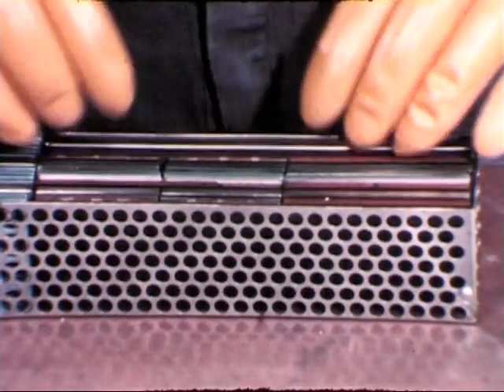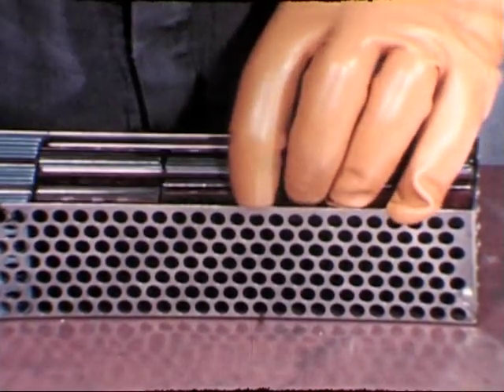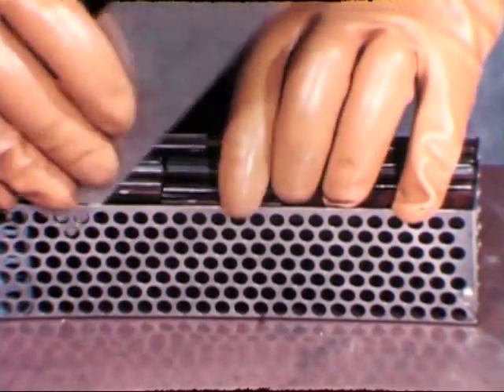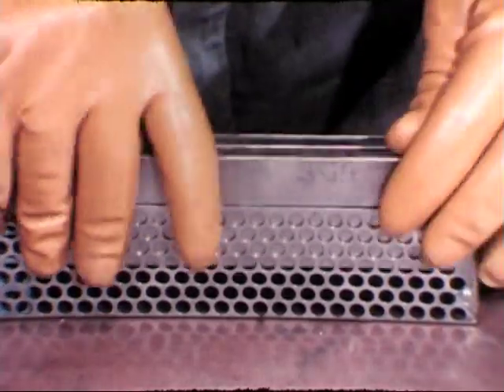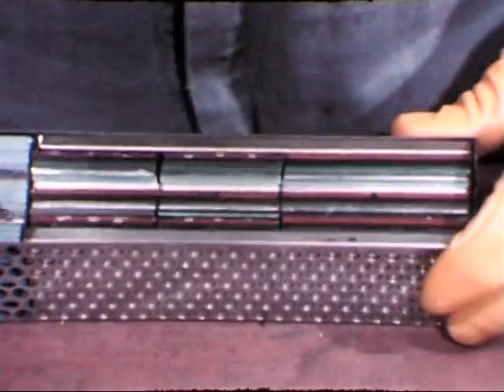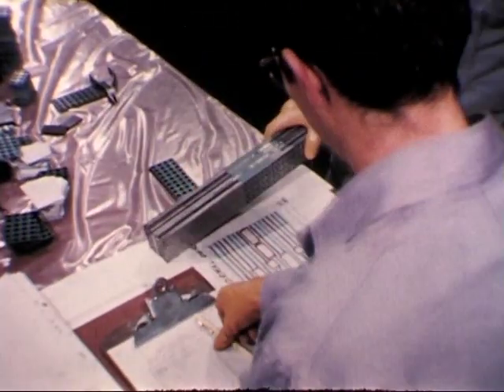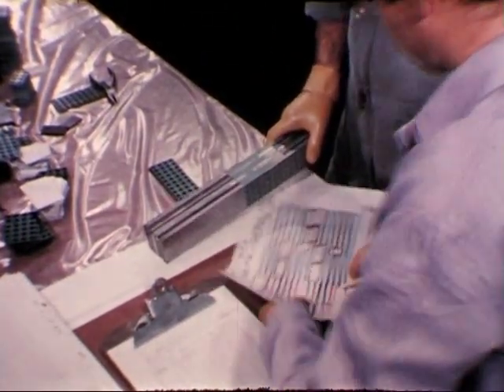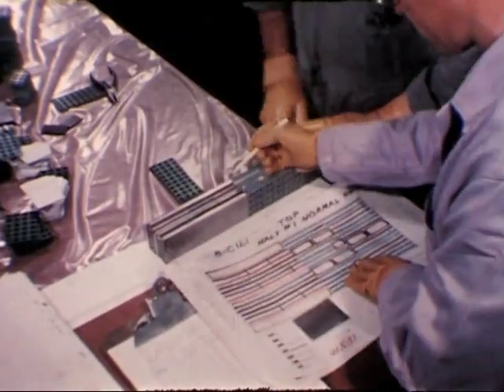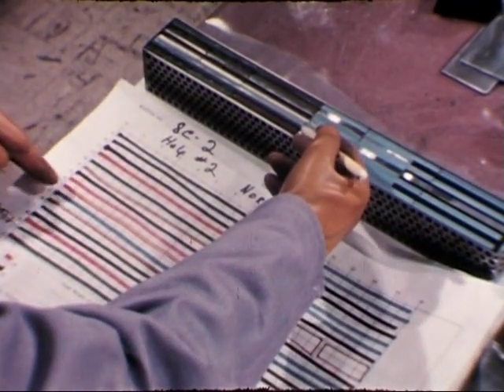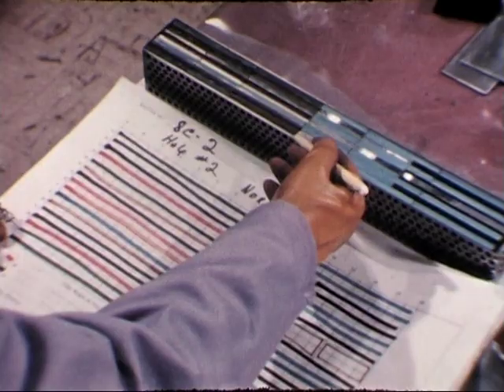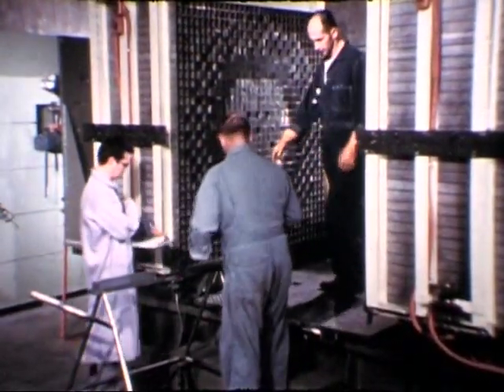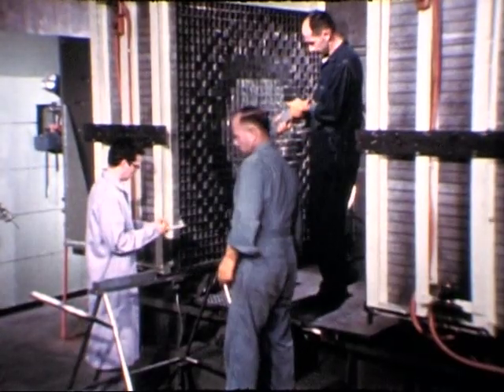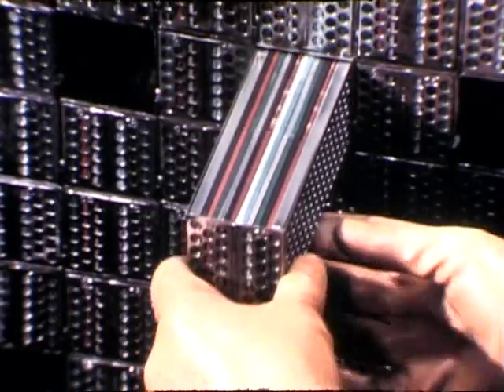To confirm the equivalence between aluminum and sodium to be used in the EBR-2, it is necessary to substitute containers filled with sodium. This same experimental procedure is used to determine the reactivity effect of the fission products which will be present in the EBR-2 fuel. As the drawers are completed, they are checked, then transferred to the adjacent shielded room. Loading of the 2 halves proceeds simultaneously until the mock-up is complete.